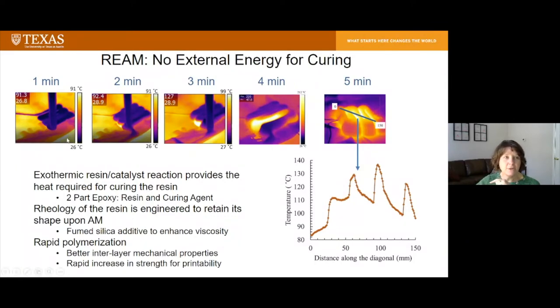You can see here, these are some infrared camera images of a very simple rectangular part as it cures. And so here you can see 1, 2, 3, 4, 5 minutes. These are time periods after initial deposition. On the left-hand side here, you can see that the peak temperature is 90 degrees C because we're printing on a heated build platform, but the material itself is room temperature as it's deposited. And because the polymerization of the epoxy is an exothermic process, you see the parts start to heat up as we move to the right. So after 5 minutes, we've got quite a few sections of the part that are above 100 degrees C.